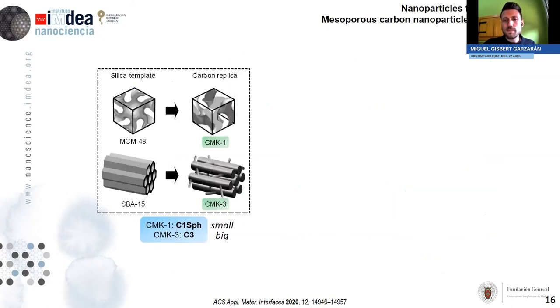Okay, so in this case, instead of MCM41 silica, we employed two different types of carbon nanoparticles, the CMK-1, which comes from MCM48 silica, and the CMK-3, which comes from SBA15 silica. And we can consider them as small and big. Of course, all of them are small, but the C1 nanoparticles, we will see that are around the 100 nanometers, and the other one are more in the micron size.